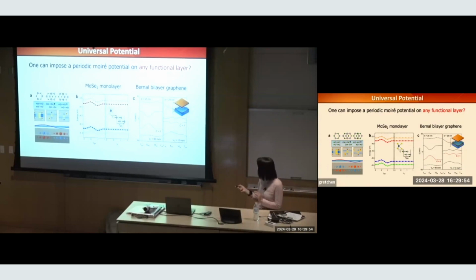Another thing I told you about the potential, how the conduction band and valence band structure in TMD is complicated. But now I put a MoS2 semiconductor on top, then at each valley, they would experience the same modulation. That's another reason to call them universal potential. If I slide the TMD versus the hBN, I would not see any change. I put a Bernal bilayer graphene. They are not twisted against each other. This is for the experts in the audience. Now I can apply the global gate, actually change the band structure of the bilayer graphene from topologically trivial to non-trivial.